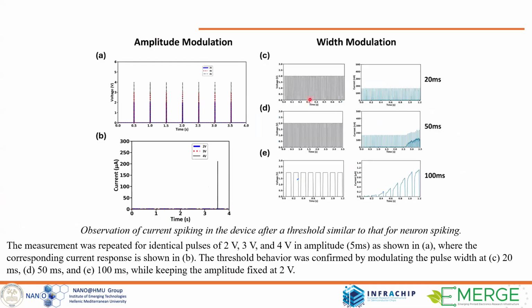This is the comparison between amplitude and pulse width modulation. Here, when the pulse amplitude was low, so 2 or 3 volts, we didn't record any spike current. Only when we increase the amplitude to 4 volts, after a period of time, we monitor a current spike in the system. Then we kept the voltage amplitude constant at 2 volts and changed the duration of the pulse, and we observed that only above 50 milliseconds of pulse duration can we monitor some current spikes, and the effect is stronger when the duration of the pulse was 100 milliseconds.